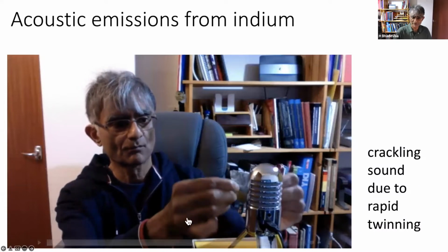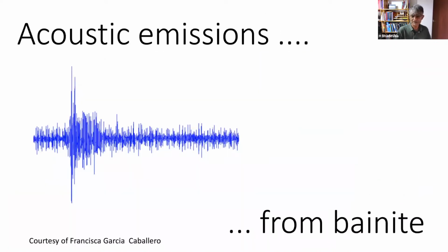Okay, so that crackling sound is because the mechanical twins are forming rapidly. So you generally get mechanical twinning when you deform at a high strain rate or when the material doesn't have sufficient slip systems. Okay, or if the stacking fault energy is right, as in the twinning-induced plasticity steels. So it's an indication of a very high rate of transformation. That rate can be calculated. And these are acoustic emissions recorded by Francisca, one of my postdocs.